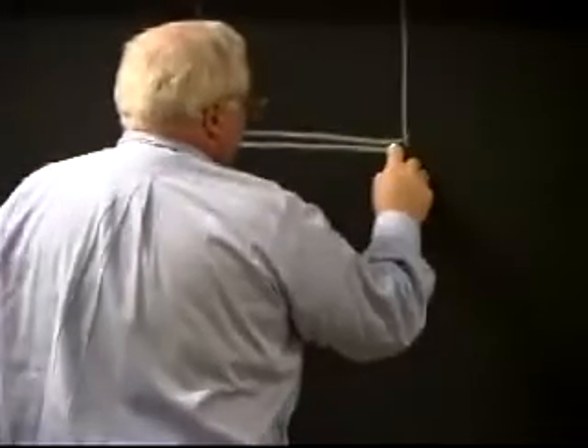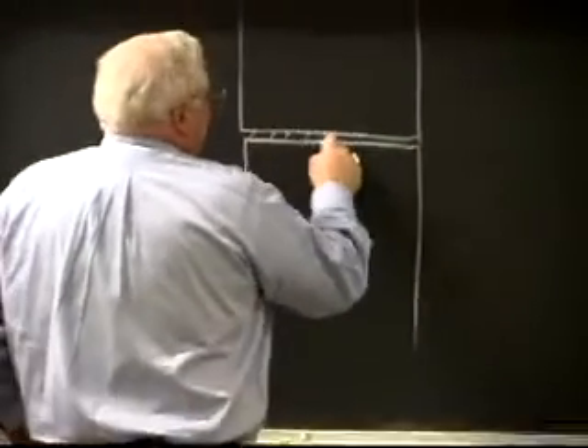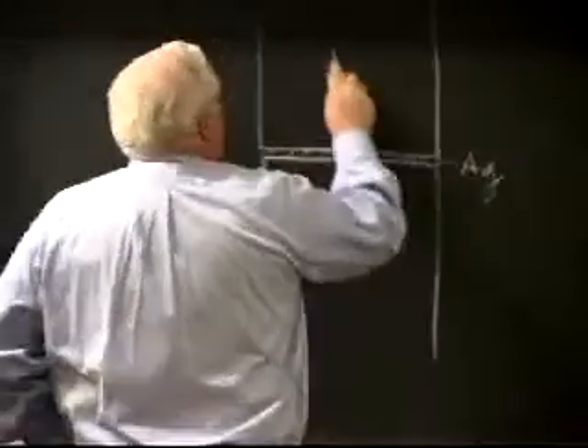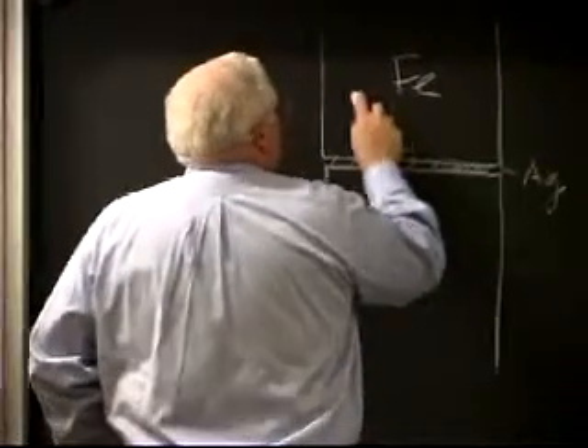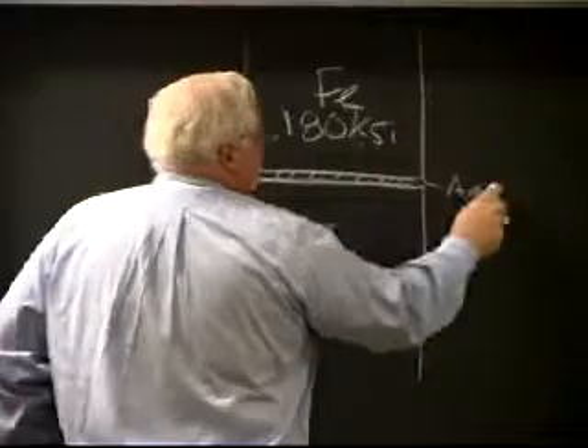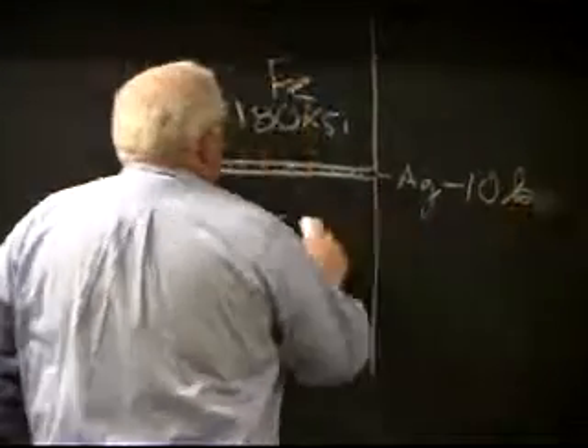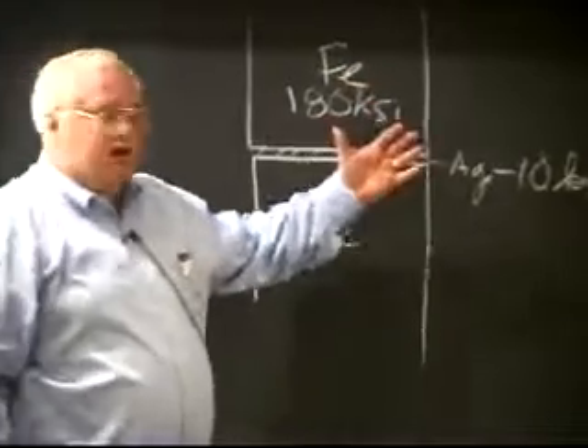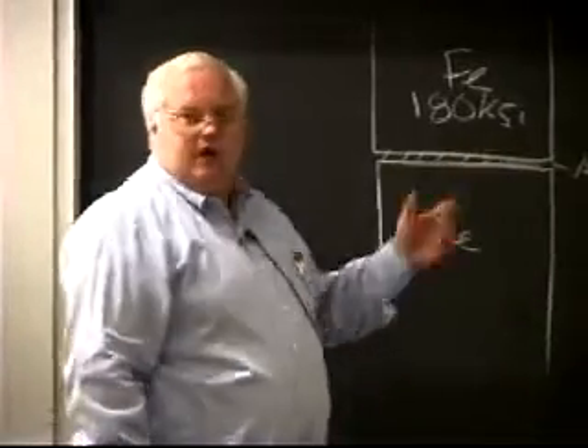Now, any questions? The next thing I want to talk about: when we were talking diffusion bonding, I talked about contact strengthening, and I told you that we would explain it when we got to things a little bit later. Well, now's the time to explain it. Contact strengthening occurs, and we saw it when we talked about diffusion bonding with silver interlayers in maraging steel. So you had a very thin layer of silver between high strength steel, and this was 180 KSI steel. This is roughly 10 KSI pure silver, but when you pulled this thing in tension, you got about 100 KSI strength.